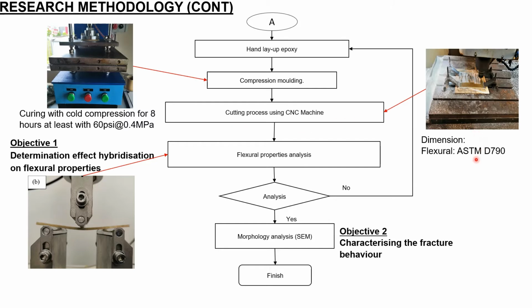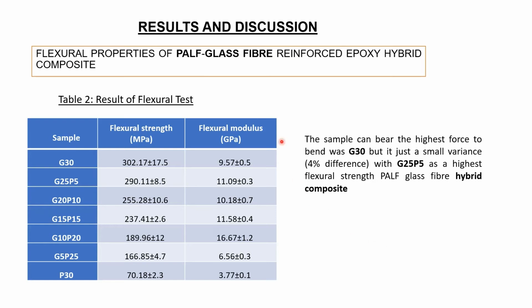The dimension we use for the flexural test is the ASTM D790 standard. And then after that, we do the flexural test, as we can see in this picture, to get objective one. And after that, we do the morphology analysis, SEM, to get objective 2. Here are the results after the flexural test.